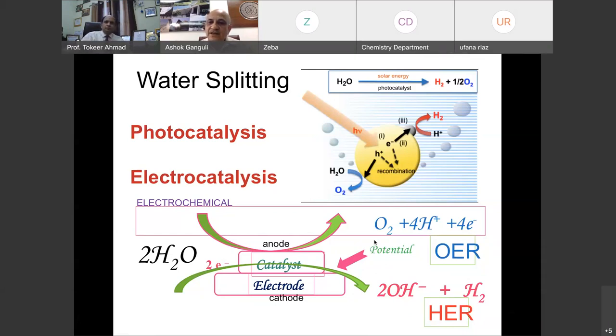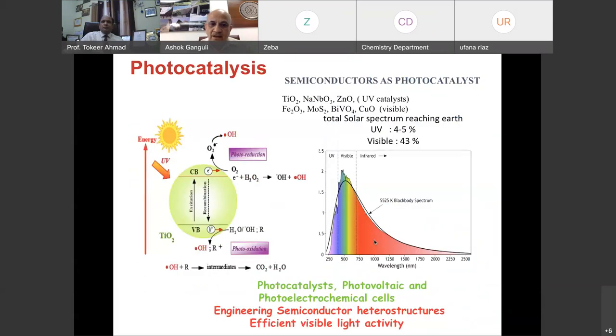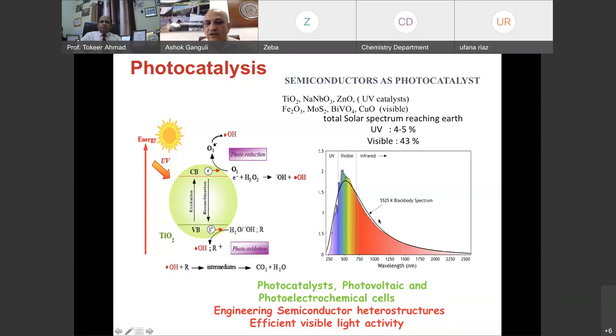You need to know the numbers for the conduction band edge and the valence band edge, which tell you what the semiconductor can reduce and what it can oxidize. Some catalysts can oxidize water, others cannot, because of the position of the valence band edge and conduction band edge. You can find out these numbers through electrochemical measurements. Our aim has been to design semiconductors made of one, two, or three materials, planning their shape and size such that the effective band gap absorbs the maximum number of photons.